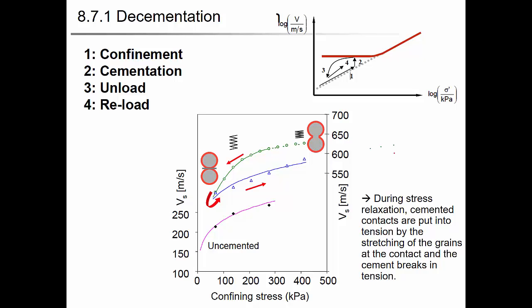And then when you decrease the stress, it follows this curve, and when you reload it, it doesn't follow the original curve. It will show you a slower wave velocity. Why? Because during the extension, when you unload it, the soil grains will feel the tension and the cement gets broken during this extension. Okay? So it's called decementation by stress release. So during this stress relaxation, cemented contacts are put into tension by the stretching of the grain at the contact, and the cement breaks in tension. So you have a lower velocity at the second loading curve. Right?